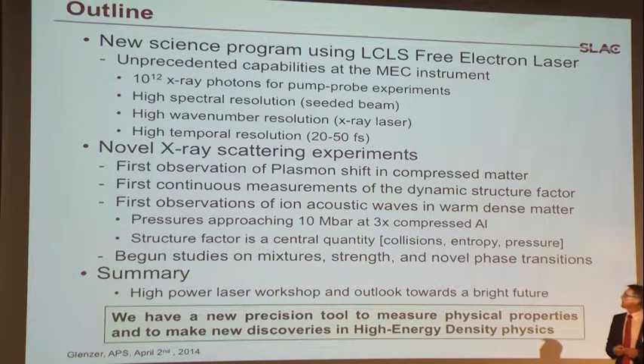I'll show you that, of course. And we have also measured for the first time ion acoustic waves in warm dense matter. And in phase space, we have approached pressures of order 10 megabar, 3 times compressed aluminum. And what we find is that the structure factor measurements that we are doing really perform a central function. They are very important to figure out collisions, entropy, pressure. In other words, to get the physical properties of matter in extreme conditions.